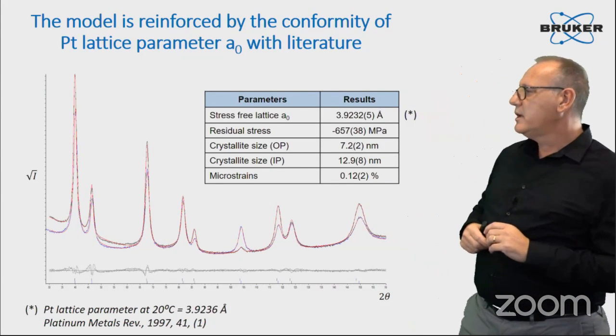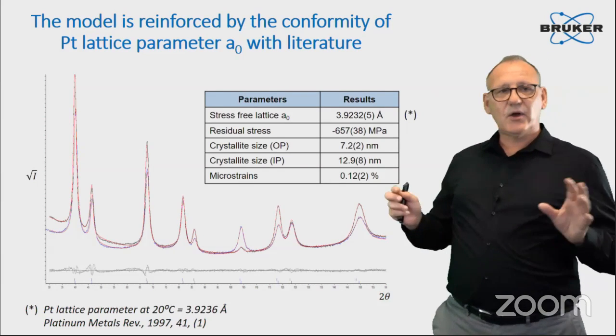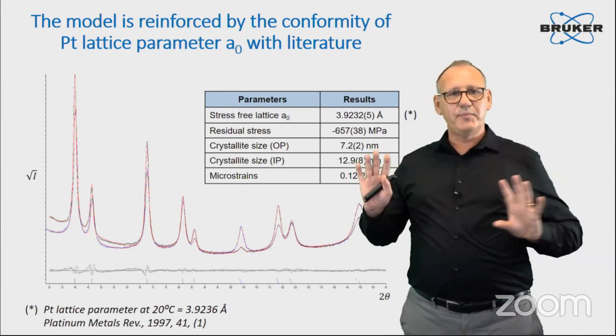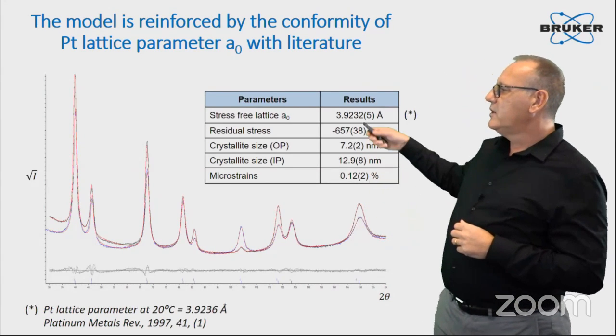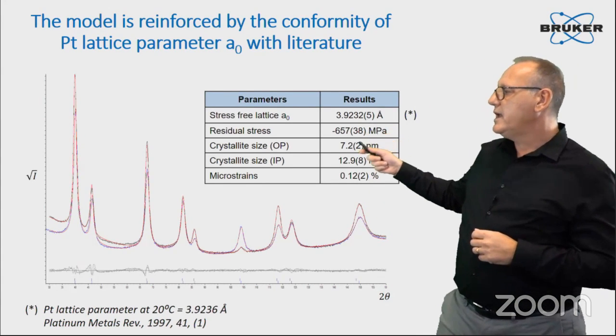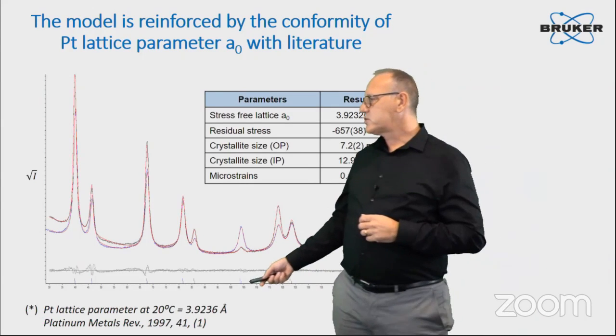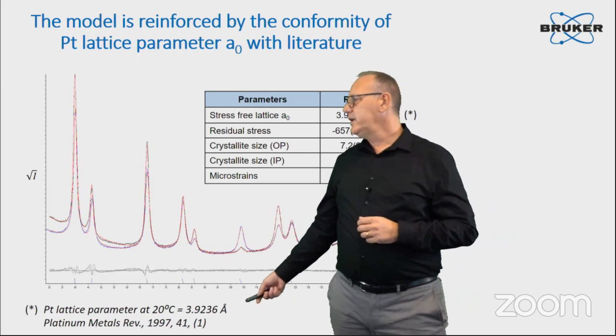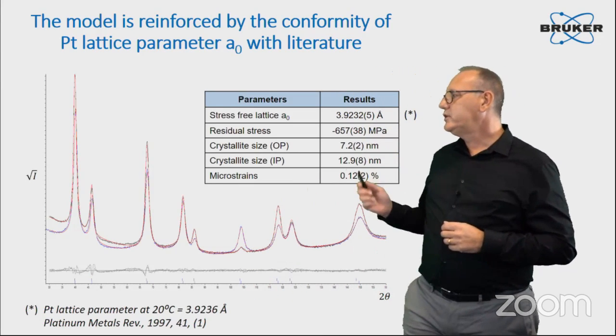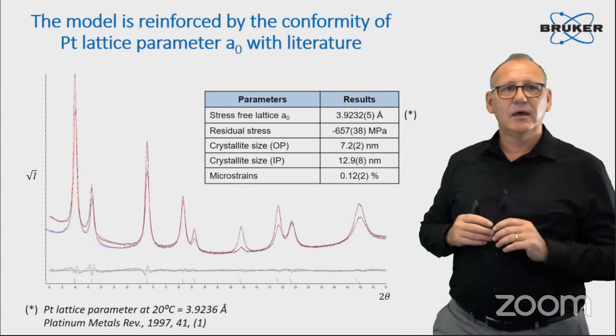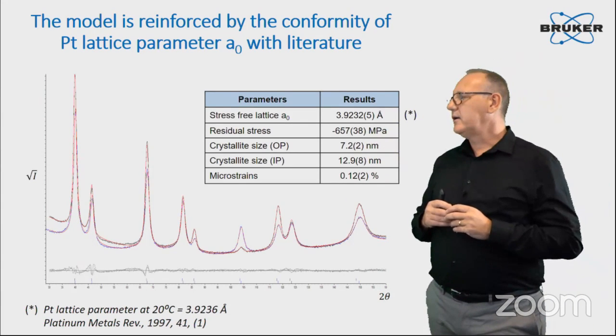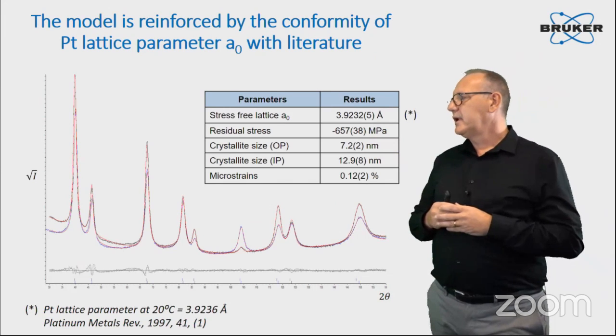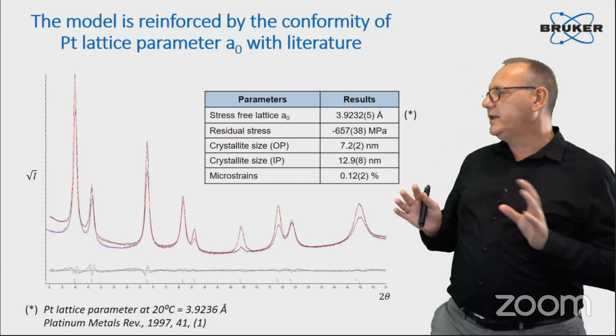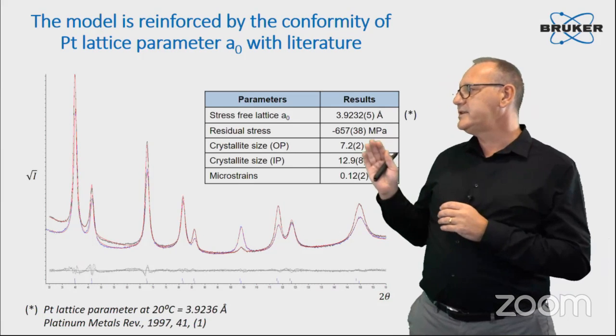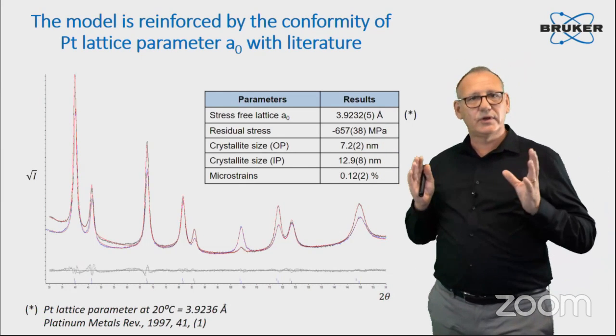And even more important here, despite the shift of the peak in all directions due to different effects, the stress-free lattice parameter we obtain is very much in line with the literature numbers we can find here in the Platinum Metals Review. This actually reinforces the model, because there are so many different effects that this is a good sign that we are back to the real stress value.